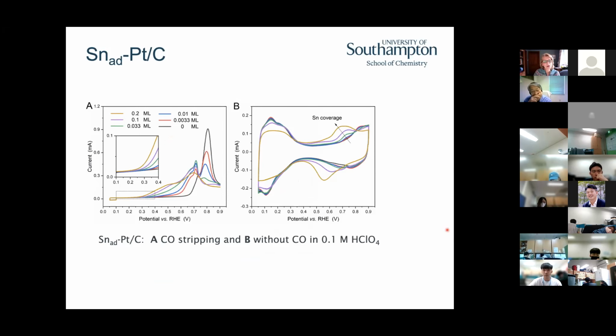Let's look at the electrochemistry. As we increase the amount of tin in the CO stripping, we're pulling the potential at which the CO stripping starts more negative. So we're getting the effect we want. In the blank CV without the CO, you can see that the oxide formation is being pulled down to lower potentials, and we're suppressing the hydrogen peaks. So very nice. It looks like the tin is really sitting there on the surface. Its redox activity is maintained, and we're seeing the effect we'd expect in terms of CO promotion.